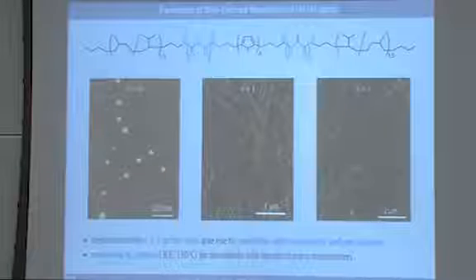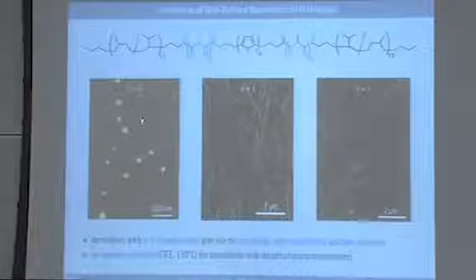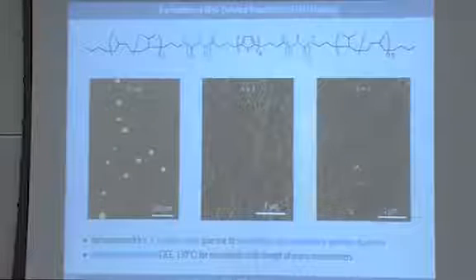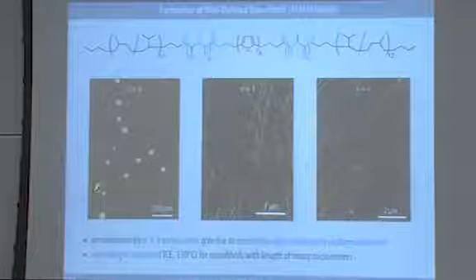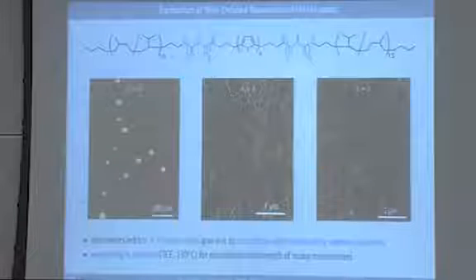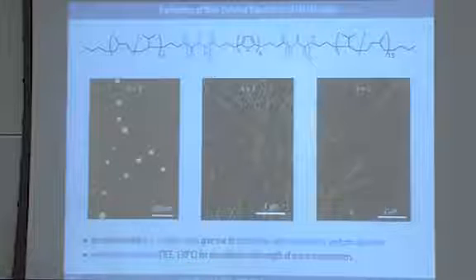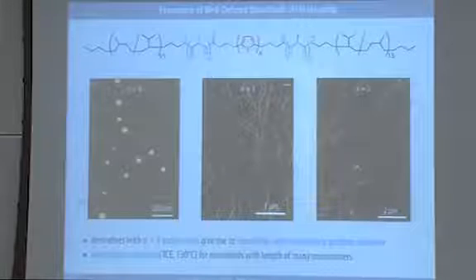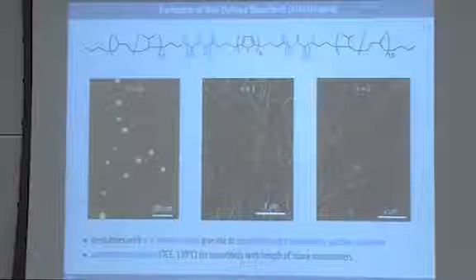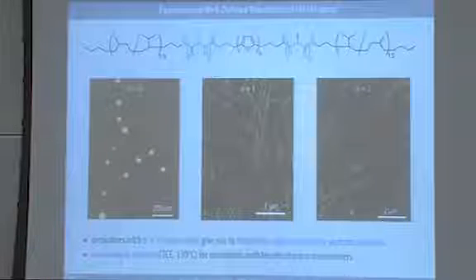What you see in the AFM images that you then obtain as you take a solution and deposit a sample on a substrate is that if the oligopeptide segments are too short, so that IR spectroscopy shows it's non-aggregated molecules, you obtain drop-like features, so no defined aggregates of any sort. But as soon as the oligopeptide segment is long enough, you obtain very well-defined nanofibrillar structures, whereby well-defined means all of them have the same diameter, and in those cases where we can actually distinguish a helicity, all of them have the same kind of helical morphology as well. And this persists even at higher concentrations.